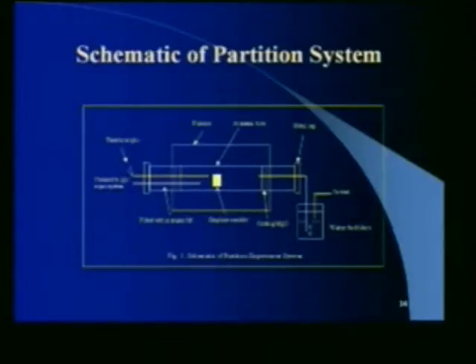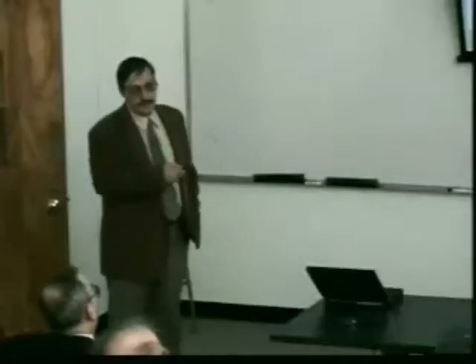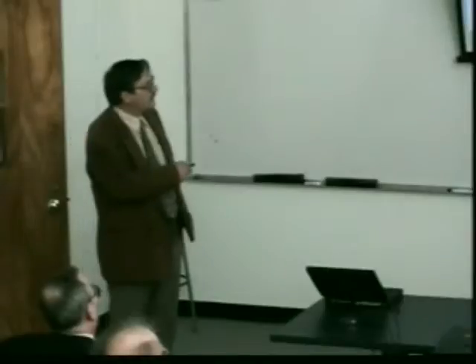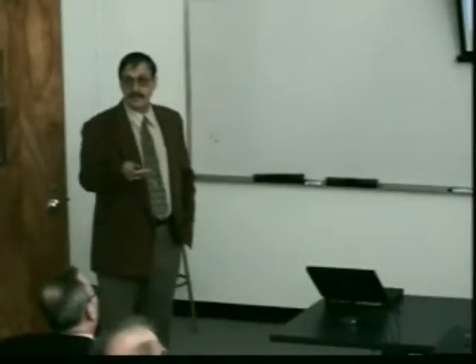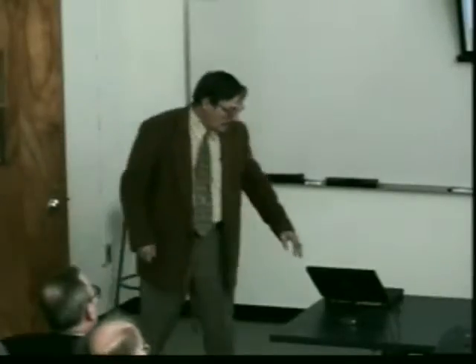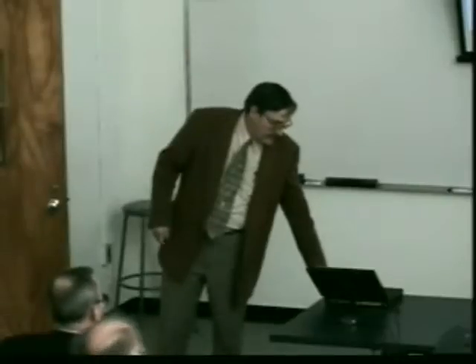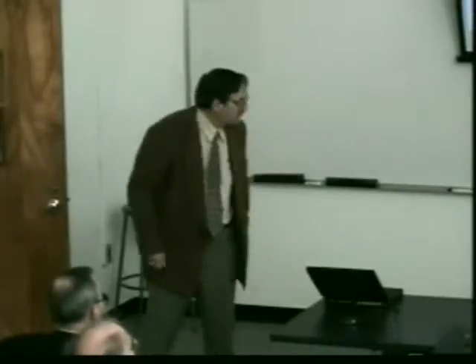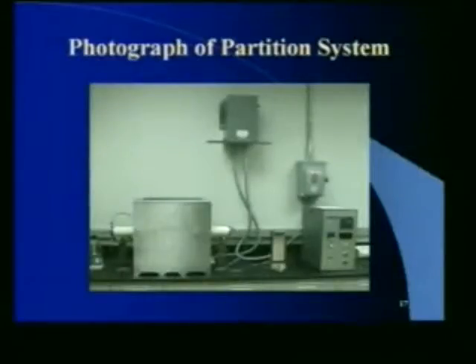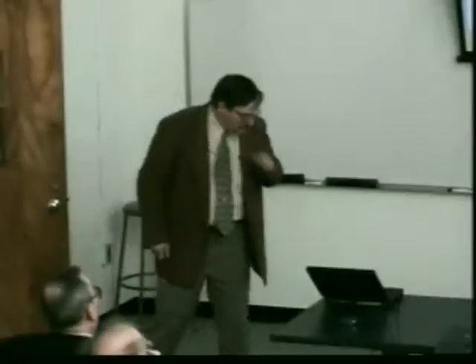You then have the initial composition. After the experiment's over, you take a small sample of this glass, dissolve it, and run ICP to determine what's left over, and then you get an idea of how much was there. And this shows our experimental system. This is, again, a molybdenum furnace capable of about 1,700 degrees centigrade. This shows a flow meter, the gas, and a little water condensation system. So it's pretty straightforward.